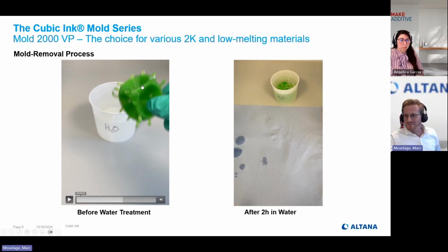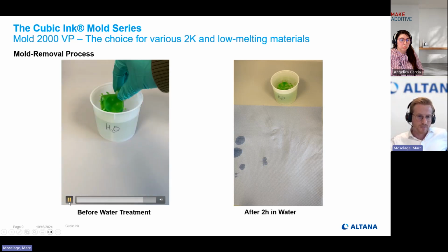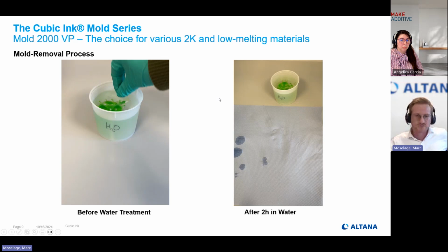This is the simple kind of a cube, right? The green one is the silicone. It's an RTV2 silicone, and it's printed inside this mold. You don't really see the mold. The mold wall thickness here is roughly 600 micrometers. So this is after printing, and we just put it into water. Nothing special. Cold water from the tap, unstirred, and this is the result after 2 hours.